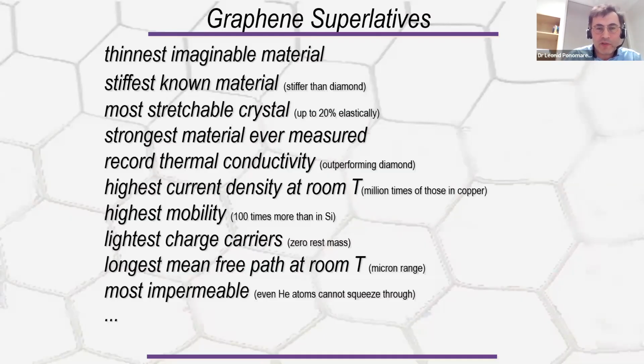But not only mechanical properties are very exciting. It outperforms all known materials in terms of heat conductivity and current conductivity at room temperature. And if we get more technical and look at properties such as mobility or effective mass, then graphene is also a champion in many respects. It has the highest mobility, the effective mass is essentially zero because of the very special band structure of this material, and it also has the longest mean-free path.